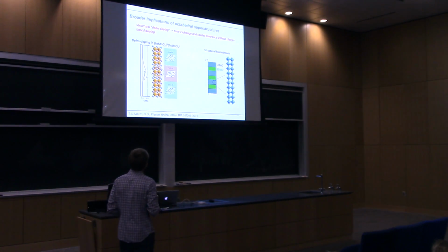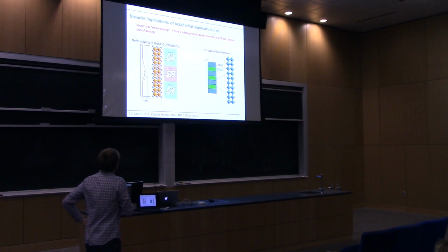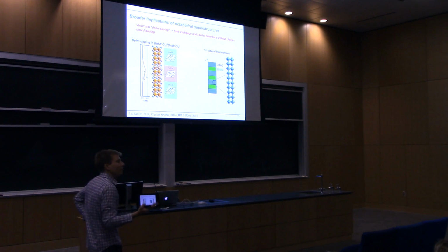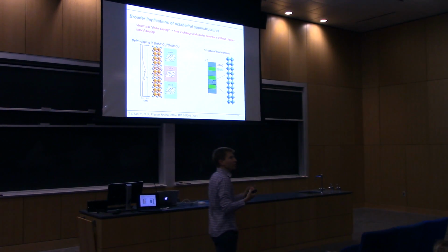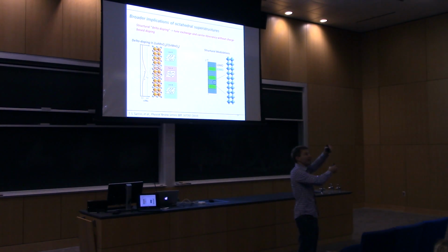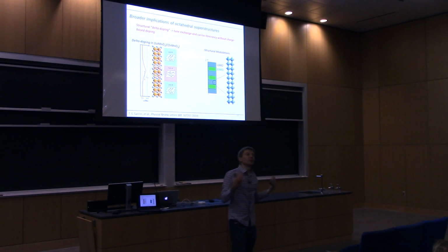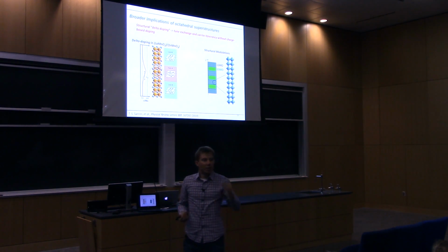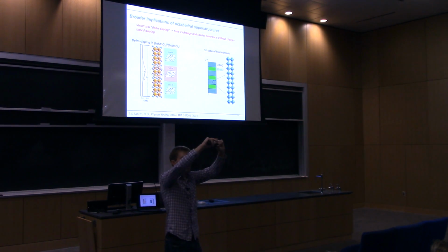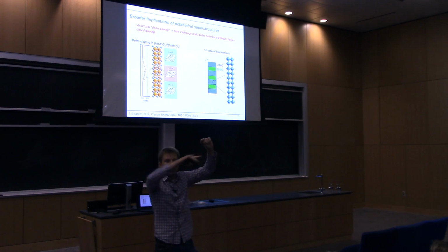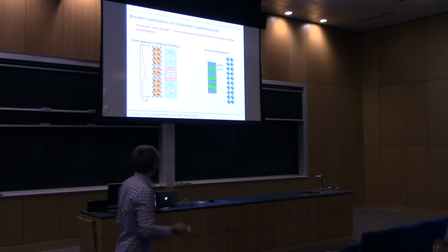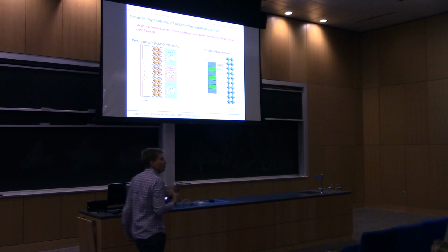All right, so why do I think this is interesting? Well, first, there's been a lot of work in our field looking at heterovalent superlattices. For instance, we take lanthanum manganite and strontium manganite, we have a d4 and d3, and we get some charge transfer at that interface. This is kind of like delta doping, which has been done in semiconductors. We can insert certain layers that have a different valence, some of that charge leaks out, and that locally confines some property. What we've done is the structural equivalent to that.